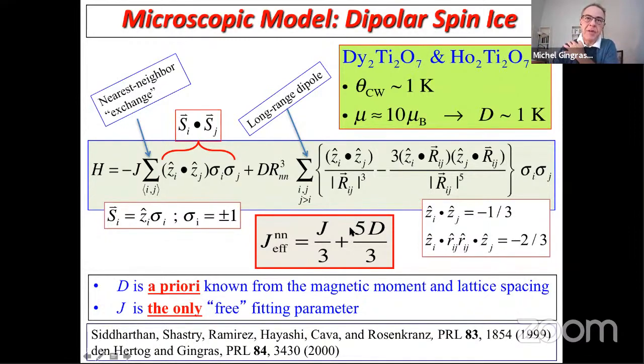These factors of one-third and the 5 simply come from the geometry of the lattice, essentially. So this model is nice because a priori, the magnetic moment is known on these systems, and we know the lattice spacing. So the dipolar coupling constant D is known a priori, it's not a fitting parameter in the system. Another way to say that: for the crystal field energy levels that I mentioned earlier, we know the wave functions from inelastic neutron scattering, by doing crystal field analysis of those measurements. So we know the wave functions in the crystal field doublet, and so we know the magnetic moment that the doublet carries. It's 9.9 Bohr magnetons. So D is very well known. And so J, this nearest neighbor coupling term, is our only free fitting parameter.